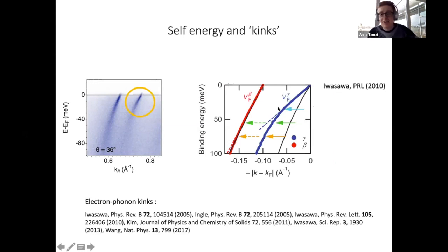So I think that this is not the right interpretation of this frequency dependence, for 2 reasons. Well, first, you can argue how clear these energy scales are in this analysis. Second thing, this interpretation relies on the fact that this would be a linear Fermi liquid in the entire frequency range of the entire phonon bandwidth, and this is not really the case in this system, which is a Fermi liquid only below 25 Kelvin, which is a much smaller energy range than the phonon frequencies.